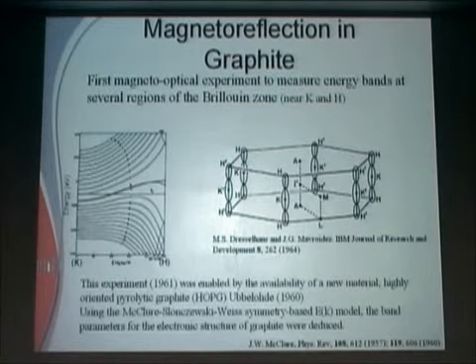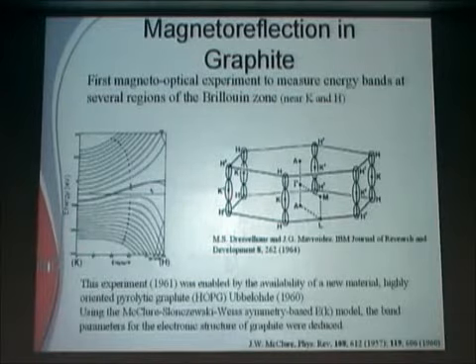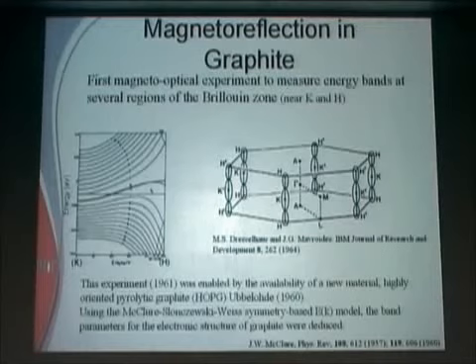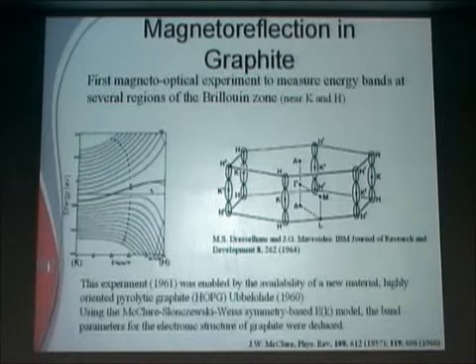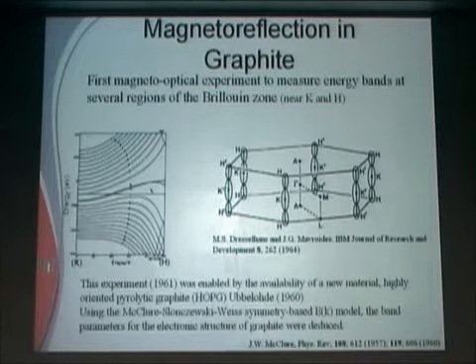The most important outcome of this work, relevant to what we're doing today, is that when we started these studies, it was believed that the holes were at the K point and the electrons were at the H point. When that belief was rationalized into studying the electronic structure, there were many experiments that didn't fit any model. By properly identifying which pocket corresponded to electrons and which to holes, everything fell into place and the electronic structure was established.